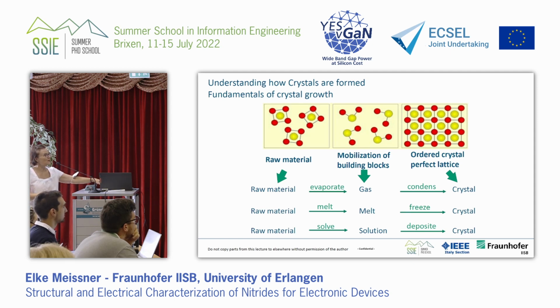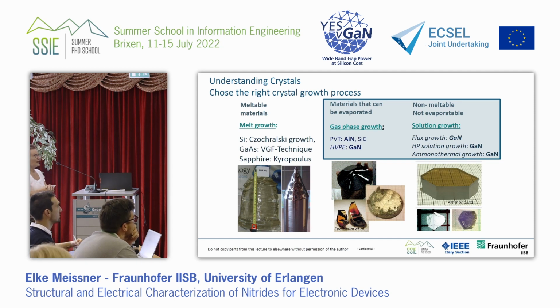Now you have to find what is the best growth method. And finding the most fitting growth method for the material that you have also means that you may be able, better or less well, to achieve the most perfect lattice. If you choose the wrong method, for example one which doesn't fit well to the material, you end up maybe with a material that has more defects, rather than if you choose a growth method that fits very well to the material and the material properties, and you end up with a more perfect crystal. And at the end, this counts for epitaxy.